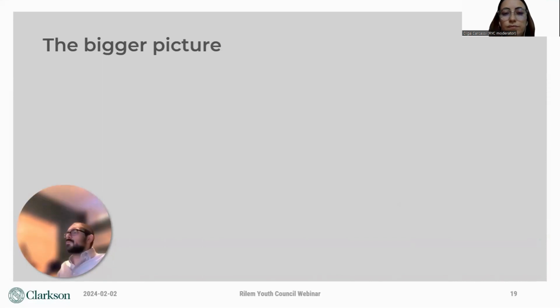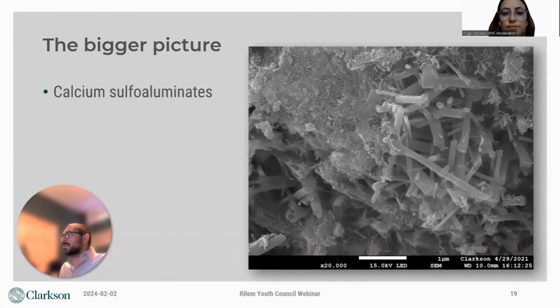So clearly we have a lot of work going on and we're trying our very best to develop lunar concrete technology and solve the various problems that appear along the way. But at this point, I think it's very important to acknowledge that our part of this work is small. There are so many other material technologies being developed that are just as promising, if not more promising, than lunar geopolymers. There are calcium sulfoaluminate precursors on the moon that could be used to make ettringite-based cements. This image shows the needle-like ettringite crystals that are the basis of these high early strength binder systems.